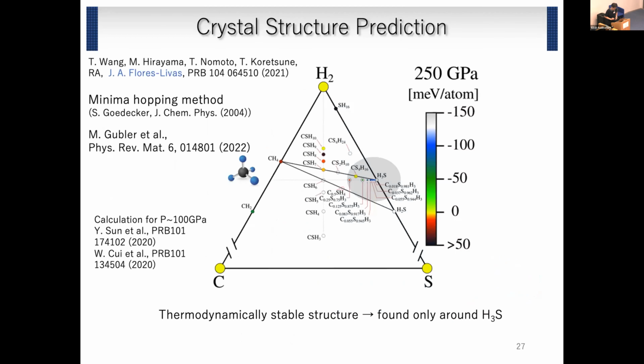Recently, José Flores-Livas did an extensive structure prediction calculation using the minima hopping method. And we found that in this convex hull, there are not so many stable structures. And actually H3S is very, very stable. And this is also, I think, a very interesting fact.